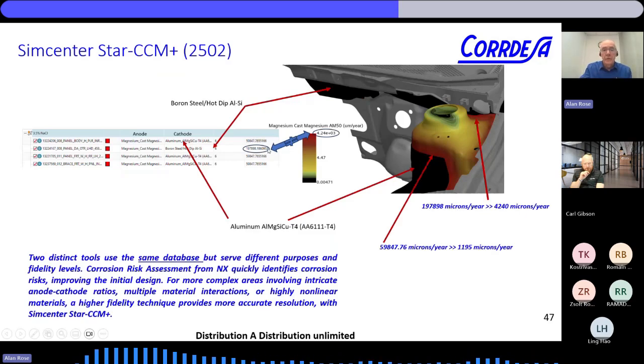So although the corrosion rates were higher in our risk analysis, they all trended in the same way. In our risk analysis, we got a high corrosion rate, but it's just telling you where the risk is. But then you take in your 3D model and you solve for the current density, it ends up being lower because of the different areas and shapes of those components.